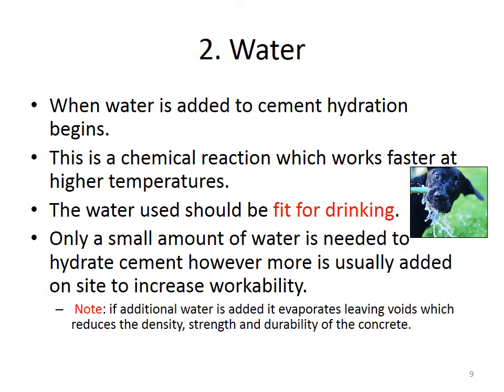The water used should be fit for drinking, as demonstrated in the image opposite. Only a small amount of water is needed in order to hydrate cement. However, more is usually added on site in order to increase workability. So just to note there that really it's the minimum amount of water, and we should try and use the minimum amount of water when we're mixing concrete, because if additional water is added, this water evaporates, leaving voids, which can reduce the density, strength and durability of the concrete.